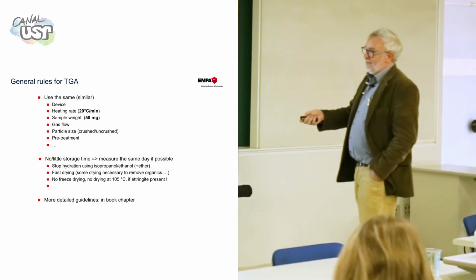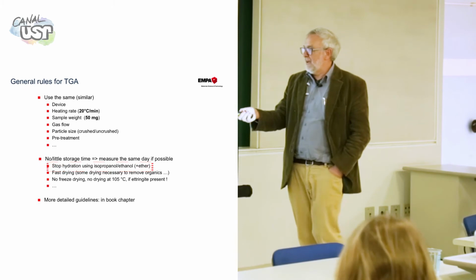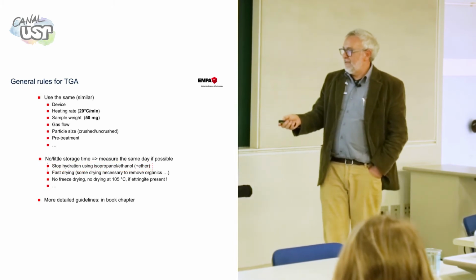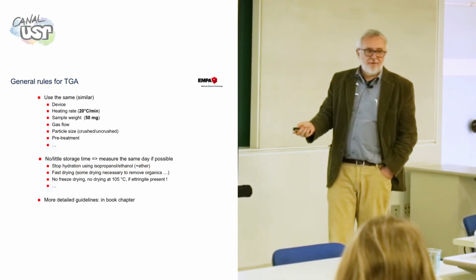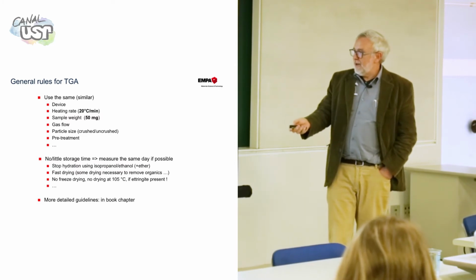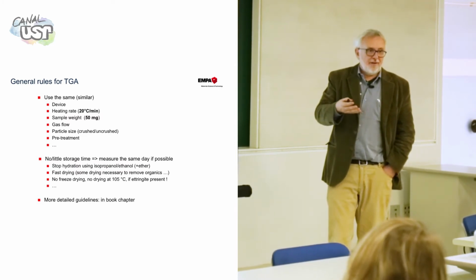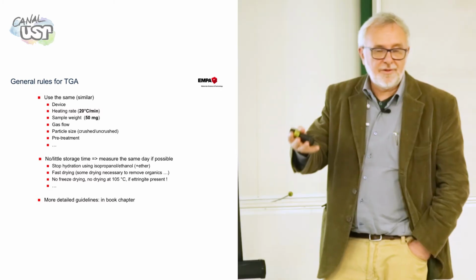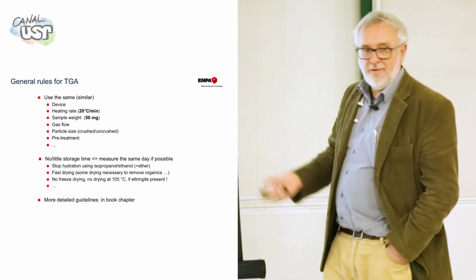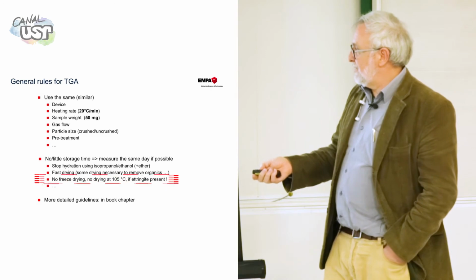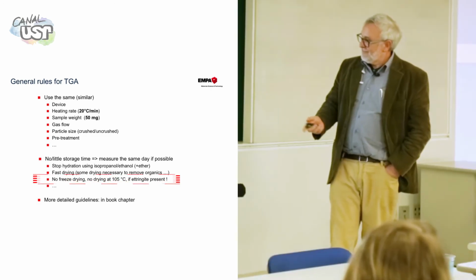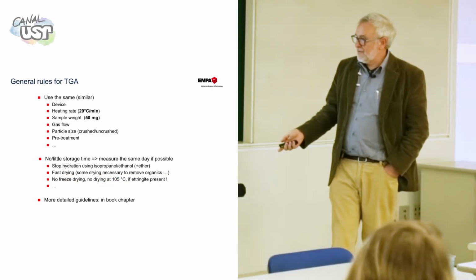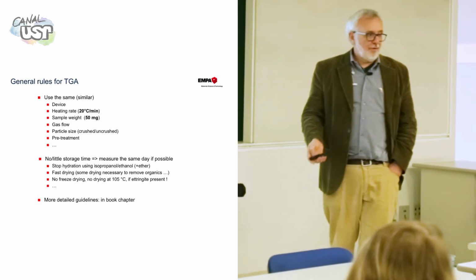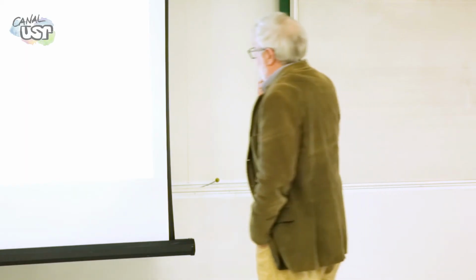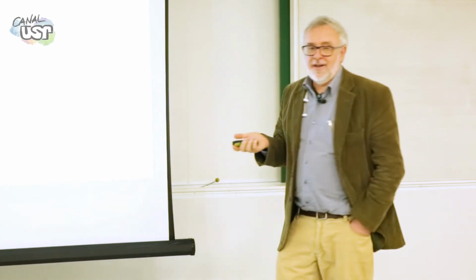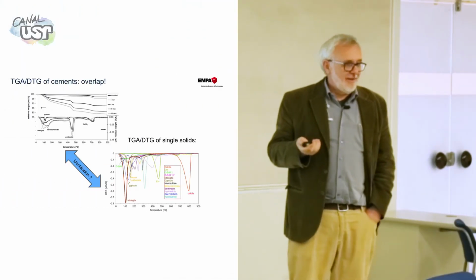Now, same day, stop hydration with isopropanol, ethanol, fast drying to remove organics, sometimes organics that are used here. Karin recommended 15 minutes at 40 degrees to get rid of the isopropanol and the ether. No freeze drying, no drying, if ettringite is present, and it's always present. And there's a book chapter on it. TGA is good for many things, but like XRD, I think worse than XRD.